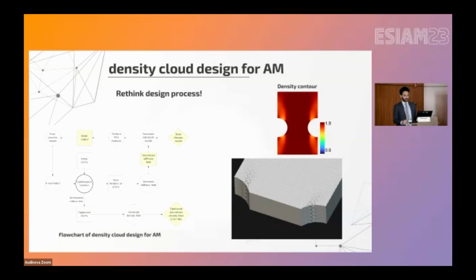We have developed this optimization technique to give us the best possible relative stiffness in the component, as you can see in the contour. Then we correlate this stiffness, which ranges between 0 and 1, to the relative density, depending on the morphology of the lattice that we choose. And then we can have this component, the notch component that you can see down there. Even though it has solid parts, it is a fully lattice structure.